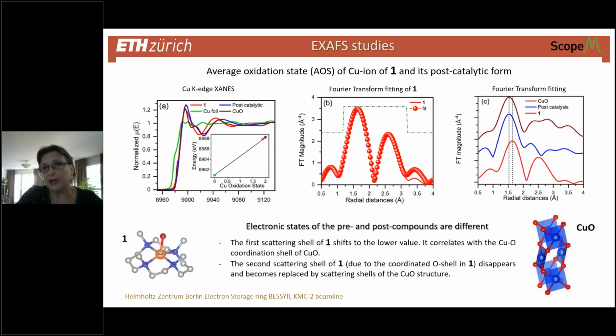It is not possible by TEM, because it's just too much mass for TEM. We won't have any decent spectroscopy signal by electron energy loss. For that, we have another wonderful technique, EXAFS studies, and for that, two PhD students, wonderful young motivated guys, went to Berlin to the KMC2 beamline and performed this average oxidation state assessment on the copper side of the compound before reaction and after the reaction.